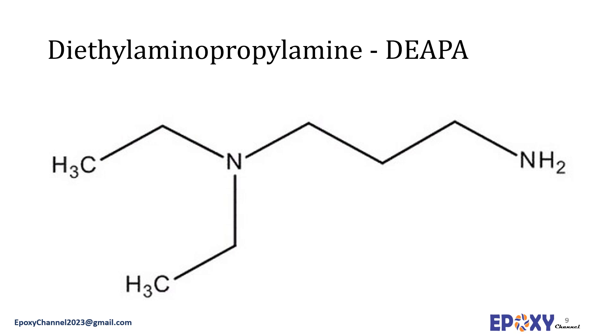Finally, we have diethylaminopropylamine, abbreviated as DEAPA. This is a water-white liquid with a fish-like odor and a molecular weight of around 130 g/mol. Its flashpoint is 53°C and it is a flammable material that may be ignited by heat, sparks, or flames. It is very irritating to skin and eyes and is used to make other chemicals and as a component of adhesives. Compared to other members, it has a higher pot life, requires additional heat to complete the curing process, and results in softer products with a lower heat deflection temperature. The structure of DEAPA is presented here.